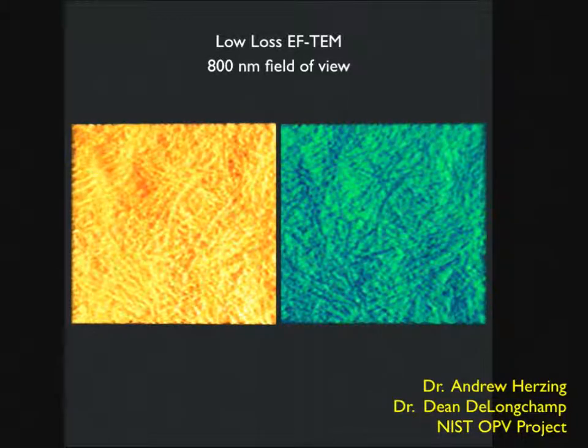So there are a number of issues with this picture. First of all, we don't really know if the red is only polymer and the green is only fullerene. There's a chance that there is some intermixing of a few percent of each component. So we don't have the resolution in the elemental analysis to fully understand it. Second of all, we don't fully understand what we want. What is the ideal morphology? Do we want 1% of acceptor in the donor or 1% of polymer in the acceptor? We're not completely sure about that.